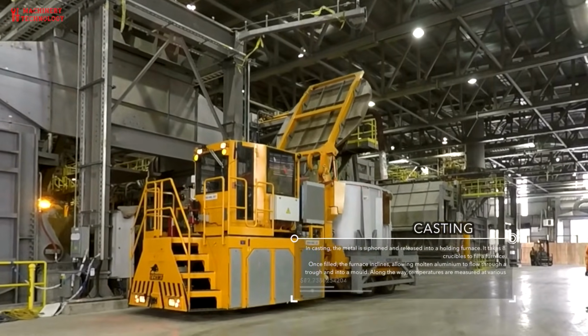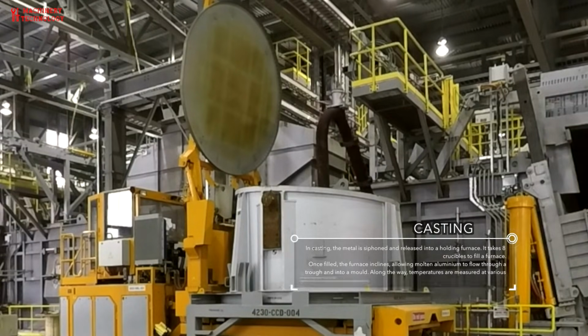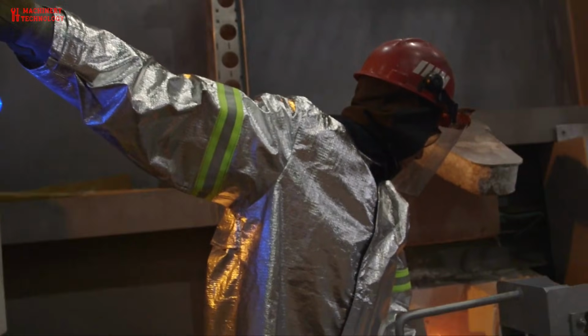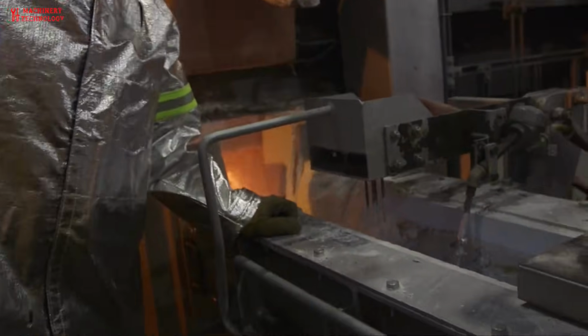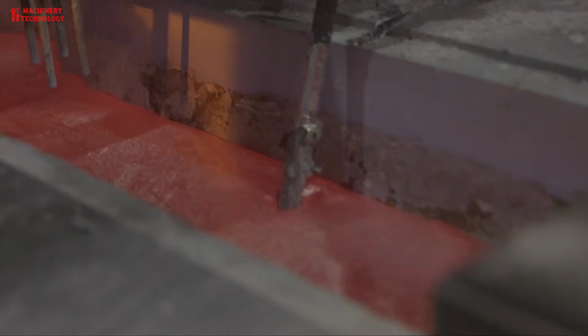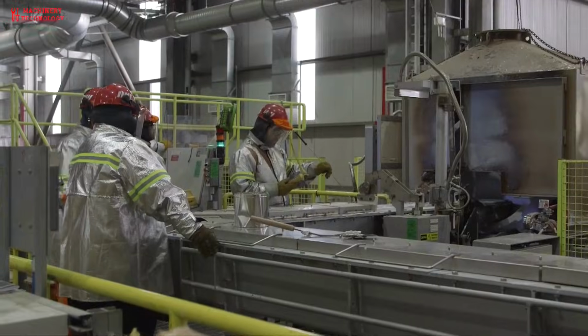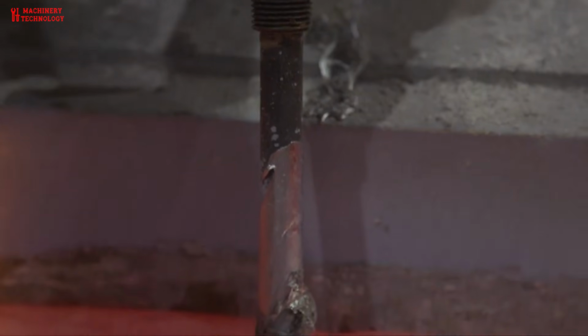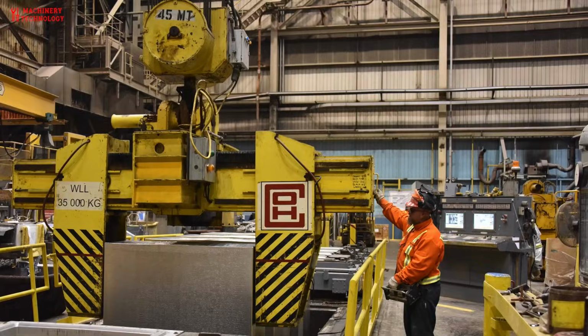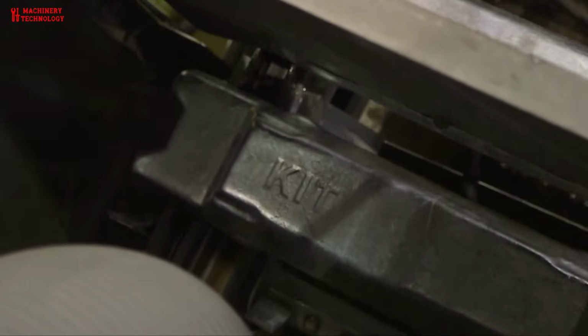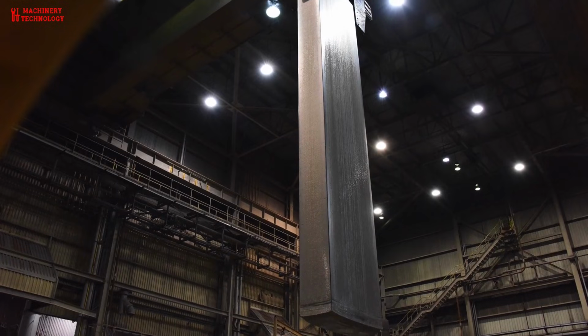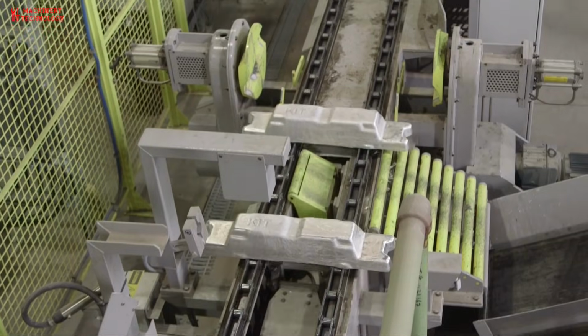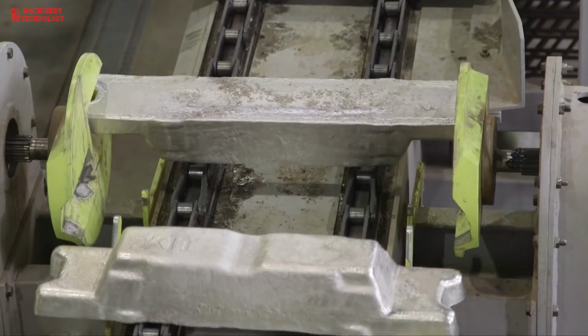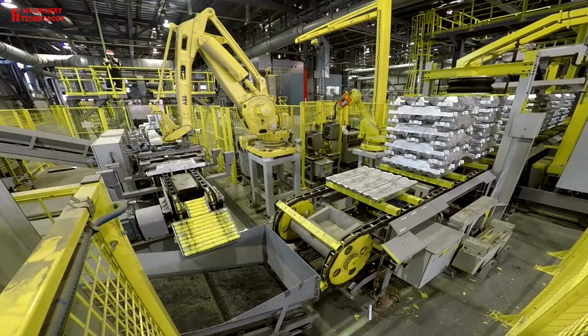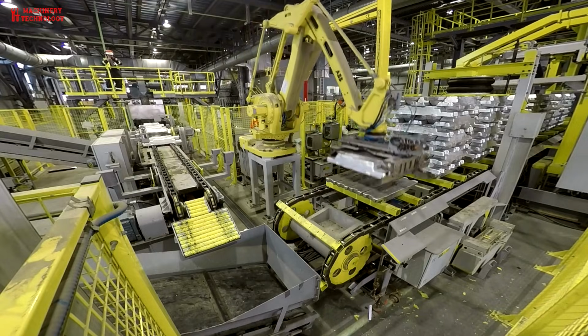At the casting shop, molten aluminium is siphoned into a holding furnace. Once the furnace is filled, it is tilted, allowing the metal to flow through channels and into moulds. Along the way, temperatures are measured at multiple points to ensure consistency throughout the casting process. Aluminium is typically cast into 3 main forms: small ingots weighing around 23 kilograms, sheet ingots weighing up to 35 tons, and sows, used primarily for remelting and further processing. Once cast and inspected, aluminium products are stacked, stored, and prepared for shipment.